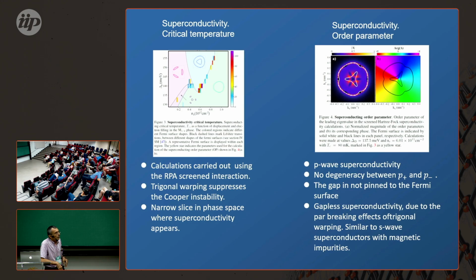Do you get it to be gapless or gapped? In order for superconductivity to be gapped, you need to start with plus k, and you have this order parameter pinned at the Fermi surface, and you need plus k and minus k to be at the same energy. So it will have no gap, that's for sure. It will be gapless, which means it will be very fragile, and a lot of perturbations will destroy it. So it's a mystery why it has been observed in the first place, but it has been observed and we have found it numerically. That's all I can say at this moment.